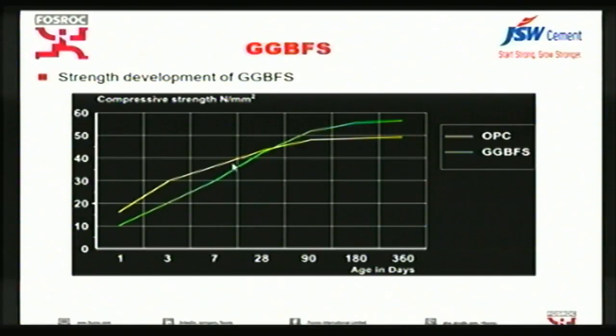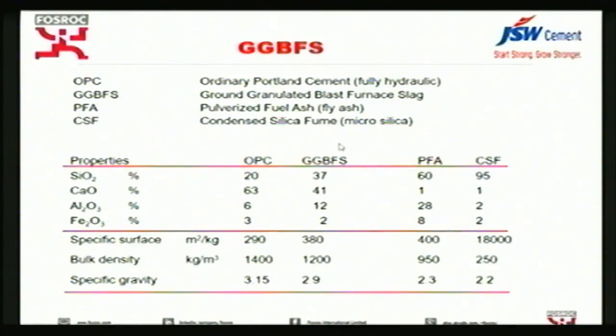But at 28 days, the strength is very close. If you take GGBFS, all the latent hydraulic properties, and compare OPC and GGBFS, the specific surface area is very close. We have a pointer here. See, if you take specific area, OPC and GGBFS are very close when compared to fly ash and silica fume. Probably this could be one of the reasons why it can accommodate so much of replacement.